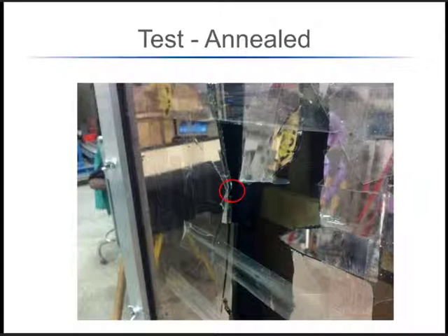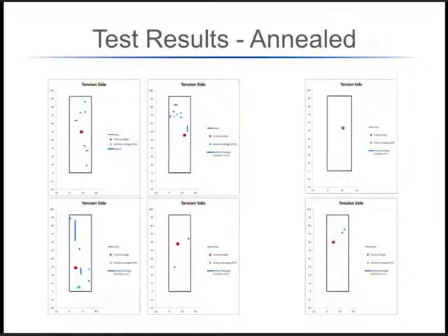And so one of the primary goals of our research was to find out, does the fracture origin correspond with the areas of damage? And we found something very interesting. Out of the 18 samples that we tested, in only 2 cases did the fracture origin match an area where there was surface damage. And those two